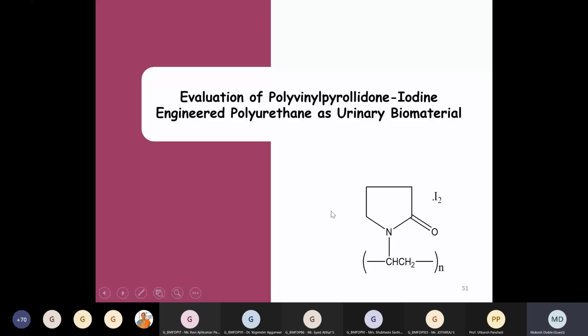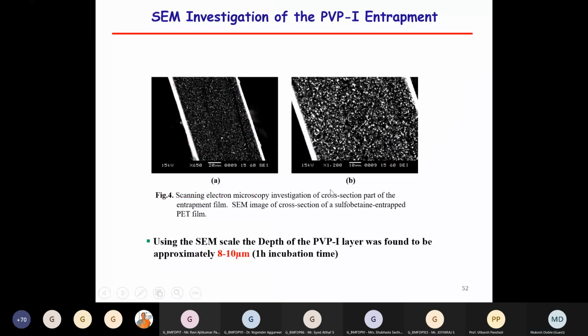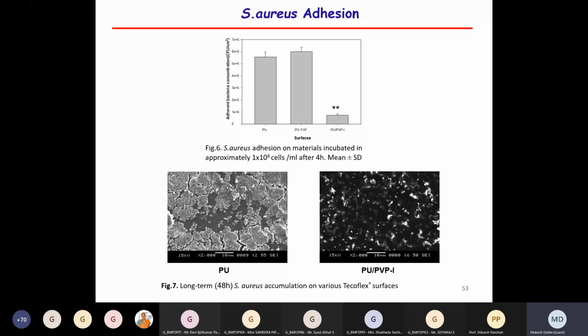We used different techniques, and I will not go too much into them, to get a very effective PVP iodine coating on the surface of polyurethane. Once we did it, we looked at how the bacterial attachment takes place. As you can see in the top bar graph, the third graph, there is a big decrease in bacterial adhesion, staph adhesion. This scanning electron picture shows you how the bacteria sit on the unmodified surface. Once we modify the surface, you can see that bacterial adhesion is completely gone.